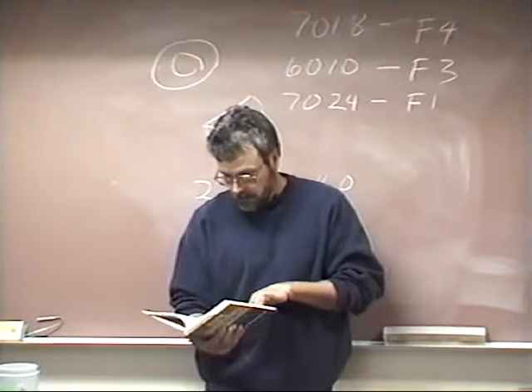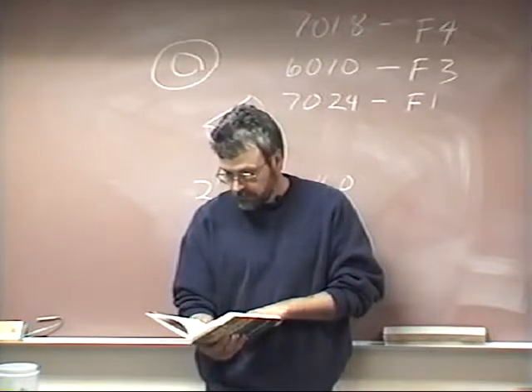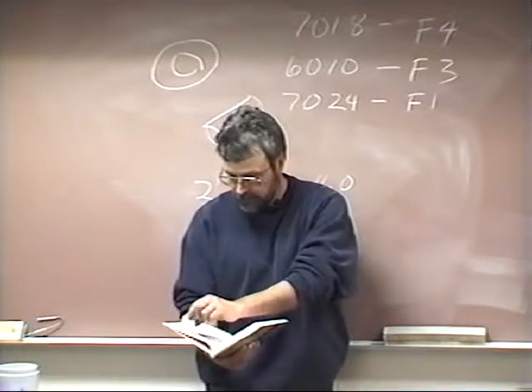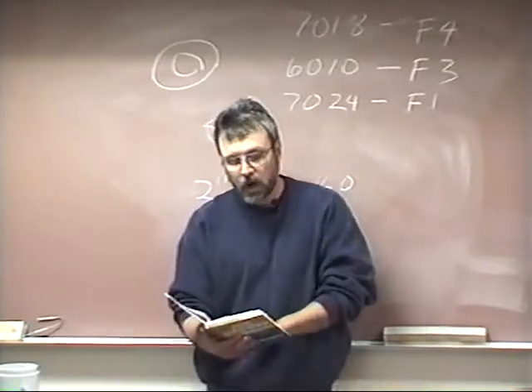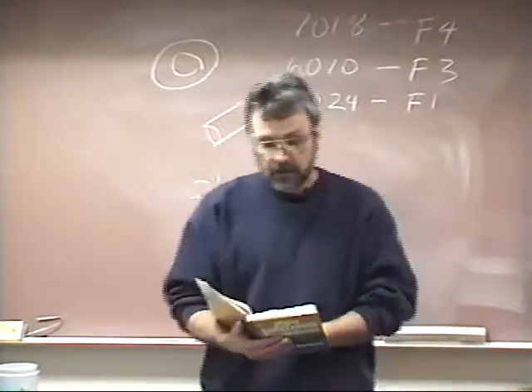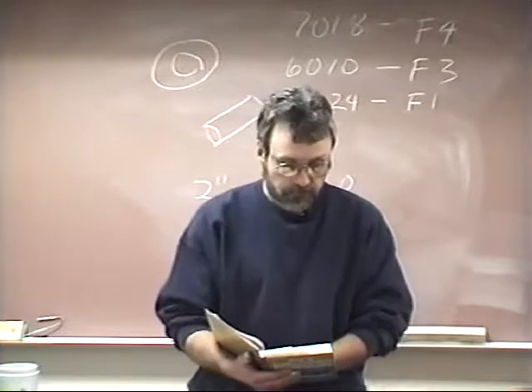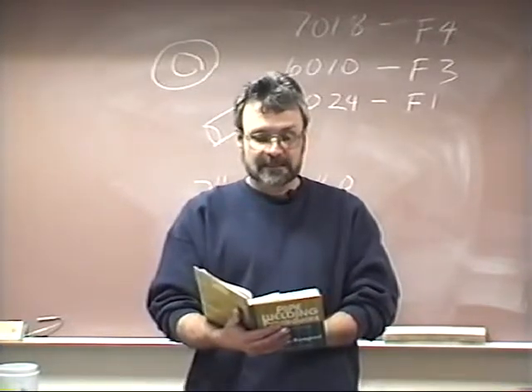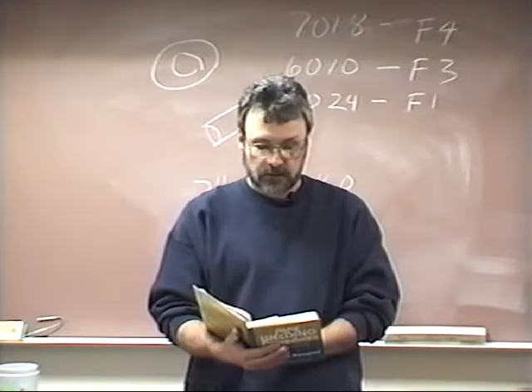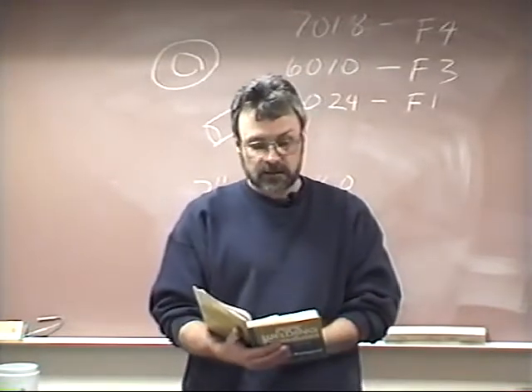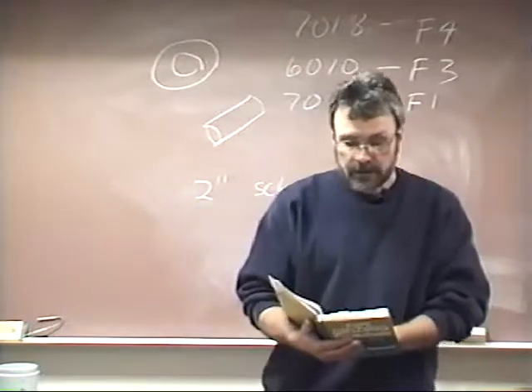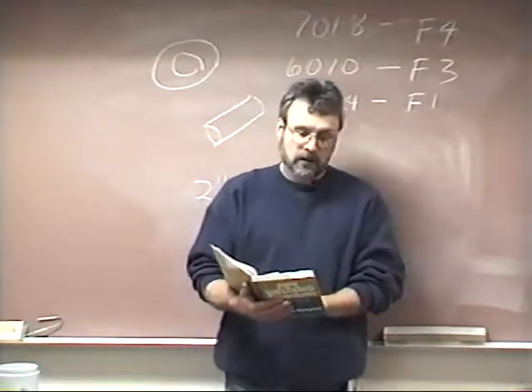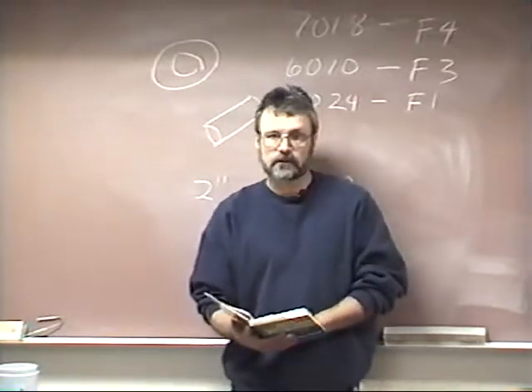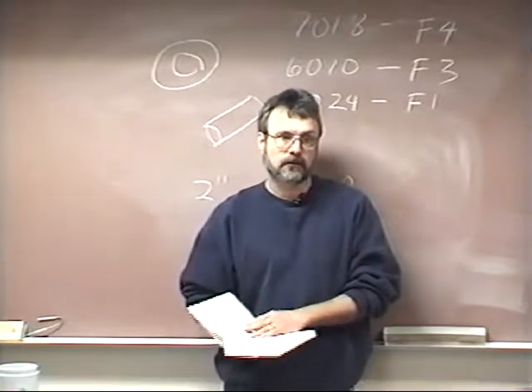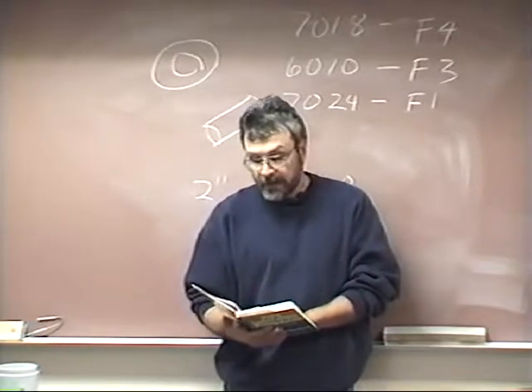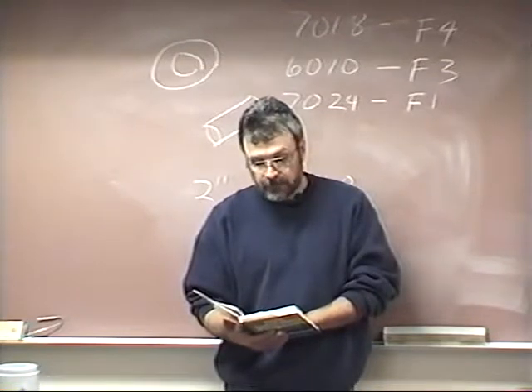So, when a test weld is completed, further visual inspection is conducted to see that the weld is free from cracks, that there are no arc strikes on the pipe surface, we've already talked about that, that the melt-through does not exceed 1/8 of an inch, that concavity of the root bead does not exceed 1/16 of an inch, that incomplete fusion is not present, that restarts and tie-ins do not exceed 1/16th to 1/64th of an inch in cavity, and that the cover pass is uniform and smooth. These are all visual things that you're going to look for as an inspector. And those of you that go on to take welding inspection technology, you're really going to get heavy into this because it's very important.